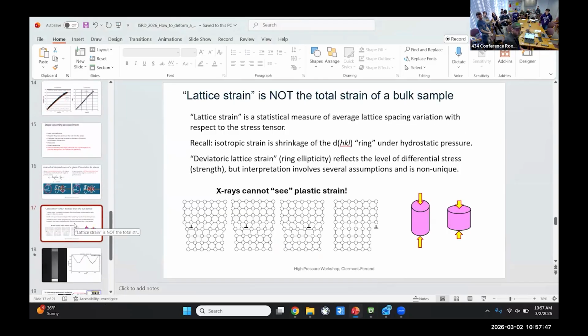Oh yeah. So we can measure the macroscopic strain from the plastic deformation, but we can't measure plastic deformation on a crystallographic level. Because plastic deformation is the movement of defects through the crystal, and we can't measure defects. We can just measure the distance between crystallographic planes. So here you have this defect in the crystal, and we're able to measure this distance, right? But we can't tell what this is. And when it's plastic, this defect will move through the crystal, and we can see that it's macroscopically straining the crystal, but we can't access that information from the diffraction patterns.